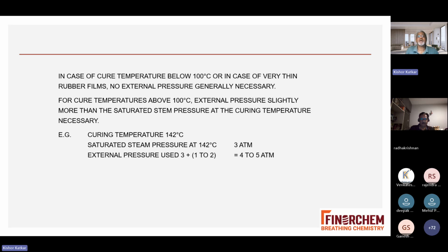I'll give you an example. Suppose your curing temperature is 142 degrees, which is equivalent to saturated steam of 3 atmospheres. So above that, the external pressure should be 4-5 atmospheres to keep the mold closed and give pressure during the vulcanization, so that there will be no faults in the vulcanized rubber.